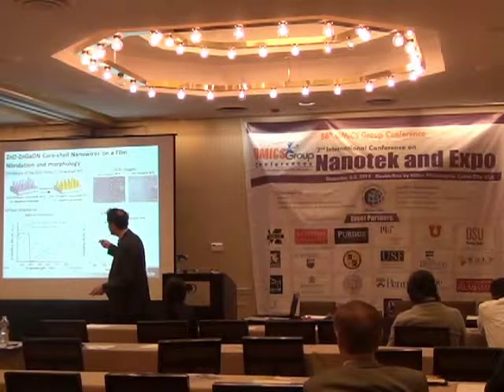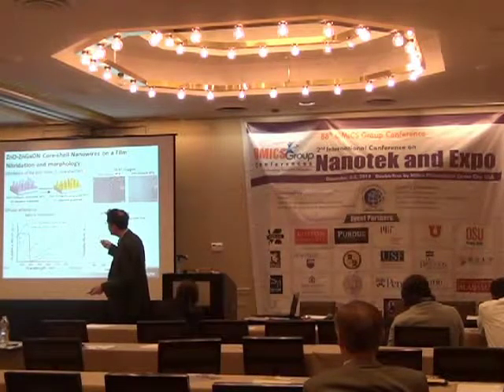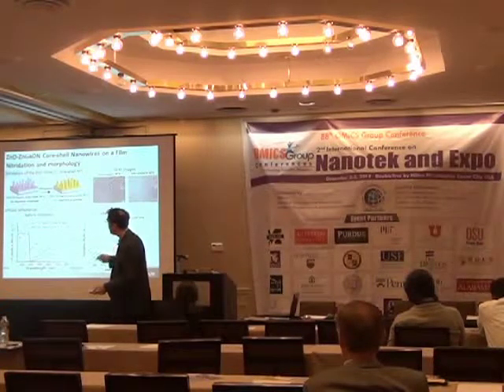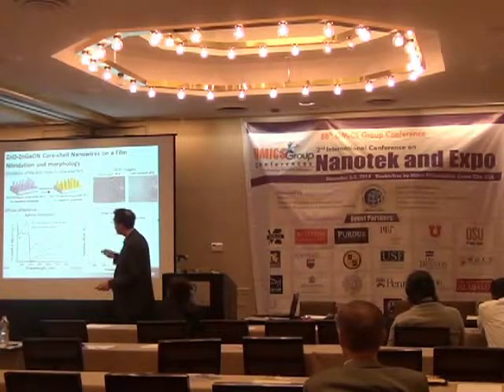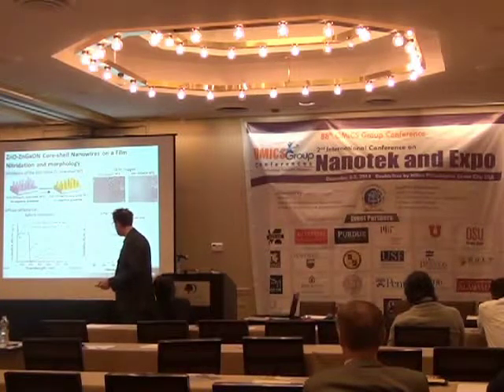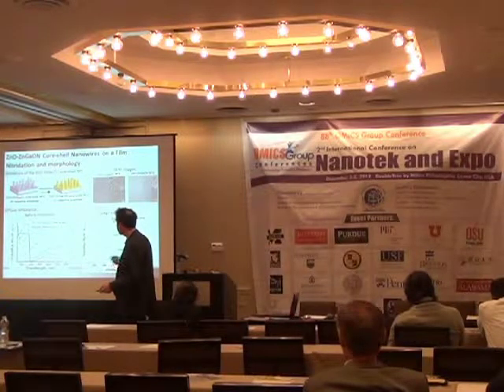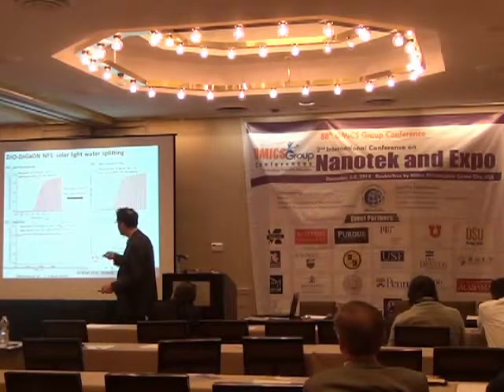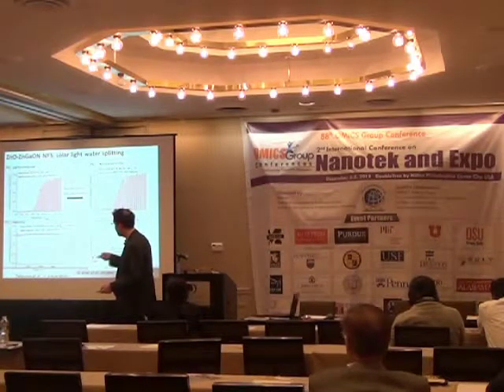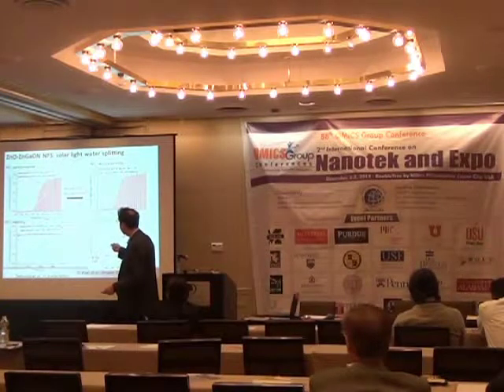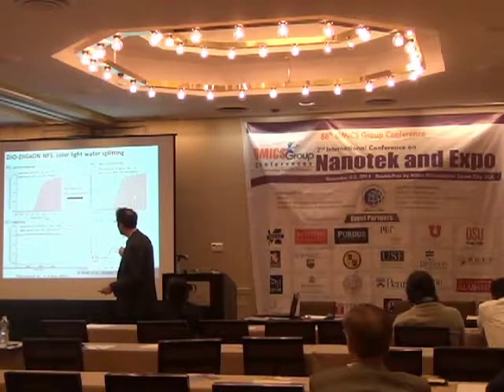So at the end, what we have is the template made of zinc oxide nanowire on a film structure, and the shell is now this material. It's a zinc gallium oxynitride material that is quite a famous material for water splitting, and that is stable and allows us to absorb a bit more in the visible region. So with that material, we have again a stable water splitting current. The photocurrent is stable in time for 30 minutes. The experiment is also reproducible, so we can reproduce our result over a month.